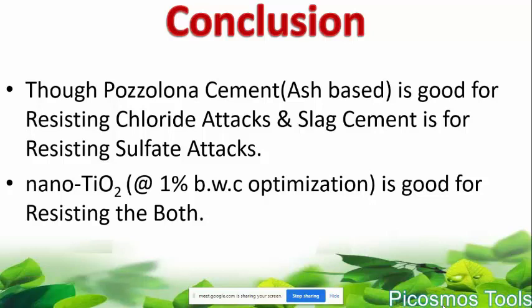Also in the aggressive environment of magnesium sulfate, the nano titanium dioxide is giving good results, the red line, at 180 days and 365 days, which we consider against the reference sample of M40 concrete. In conclusion: though pozzolana cement is good for resisting chloride attacks and slag cement is for resisting sulfate attacks, PPC cement and PSC cement, nano titanium dioxide at the rate of 1% by weight of cement optimization is good for resisting both.